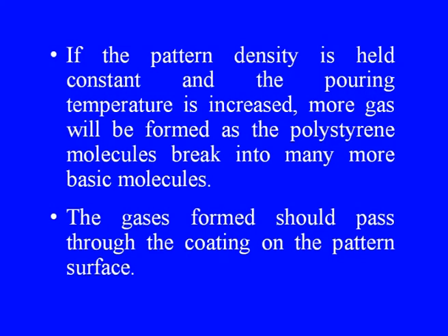The gases formed should pass through the coating on the pattern surface. The pattern density generally varies between 1 and 1.5 PCF, which further depends on the geometry and metal that is being poured. Small beads are required for obtaining relatively non-beady smooth surfaces on the molded patterns.